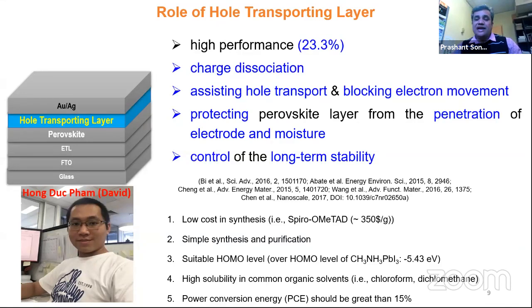If you're using mixed halide or another type of perovskite, we can tune the suitable hole transporting material accordingly. Then it should have high solubility in common organic solvents like chloroform and dichloromethane, and unless our HTM shows efficiency higher than 15%, it is not really meaningful to have an HTL. Otherwise, without HTL there are also some reports where people can get 15% efficiency. So our benchmark is to have this particular design principle.